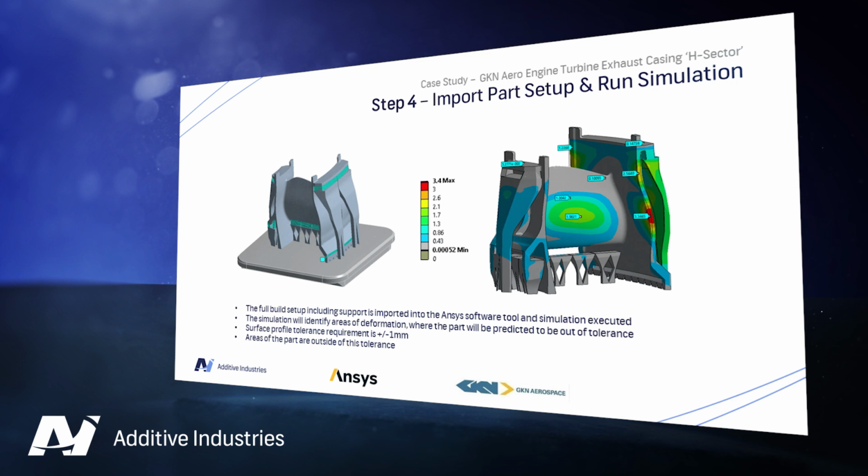Now, in the fourth step, where we performed the first simulation of the sector, we used Ansys Workbench Additive. Ansys Workbench Additive provides a very flexible environment to simulate the AM manufacturing build process with very efficient HPC performance, which is a must for large geometries like the H-Sector. The part, the supports, and the base plates were included in the setup of the simulation, and the input values that were obtained from step number 1, the calibration procedure, were used as input for the simulation. In the simulation results, we identify large deflection and large distortion in some areas, with a maximum deformation in the flange region.